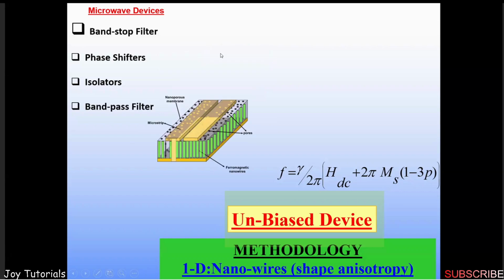Similarly, we designed also band pass filter. These are two antennas just 1 micron apart, and we fed the wave in port 1 here, and then short circuited the other end, and receive at this antenna at port 2 here, and short circuit at this end. Because of the ferromagnetic resonance, there will be coupling and there will be a band pass region. So band pass filter, and designing this band pass filter through the nanowires, one does not need an external bias field. Only the shape anisotropy is going to give me an operating frequency when we use the one-dimensional nanowires.